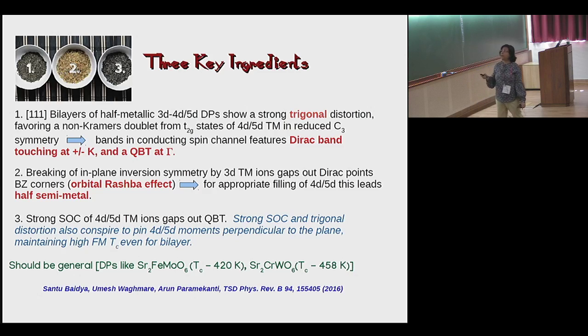And for an appropriate filling, which in this case is the d1 filling, it leads to a half semi-metal, which is what you observed in the GGA band structure. Now you introduce the strong spin-orbit effect of the 4D or 5D in this case, that gaps out the quadratic band touching and makes it an insulator, and this strong spin-orbit and trigonal distortion conspire to make the ferromagnetic Tc very high. And this should be a general mechanism, although I talked about a specific double perovskite.